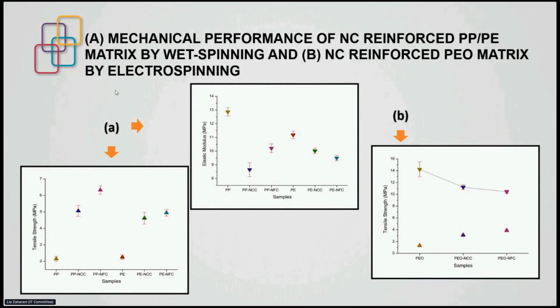When we add nanocrystalline cellulose to the polypropylene, and the nanofibrillated cellulose to polypropylene, nanofibrillated cellulose gives the highest tensile strength compared to nanocrystalline cellulose in the polypropylene matrix. For polyethylene it is the same. NFC gives higher performance than NCC.